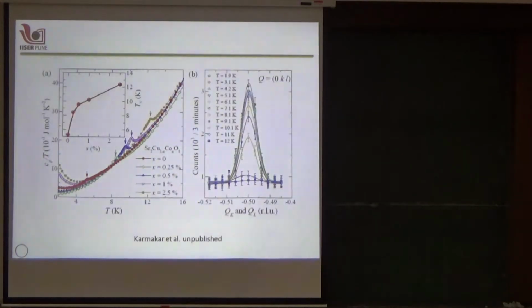We have crystals with various cobalt concentrations, and we do see that the transition temperature in zero field scales with the cobalt concentration.